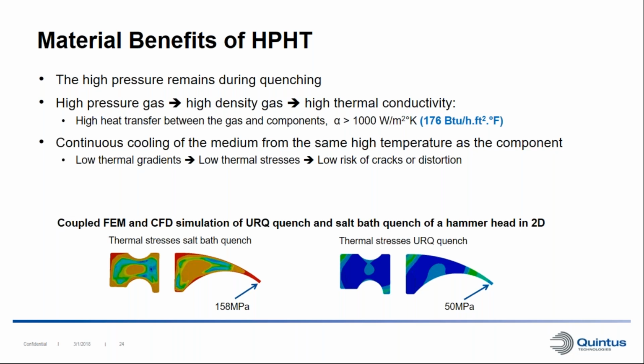If we look at more conventional heat treatment quenching processes like salt, oil, or water bath quenching, where you have a hot component that you drop down into a much cooler medium, we get this initial thermal shock of the material, and this makes a risk of cracking and distortion of your parts. However, when you do quenching in the HIP, the components being processed and the cooling medium start off at the same temperature, and then we start to cool the medium and the parts will follow. So it's a little bit of a softer quenching, and this gives us relatively low thermal gradients, which gives low thermal stresses that in turn reduces the risk of cracking and distortion.